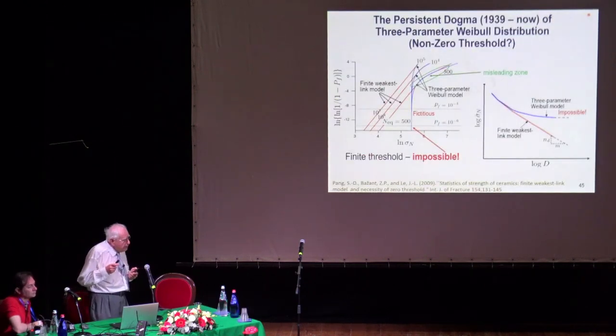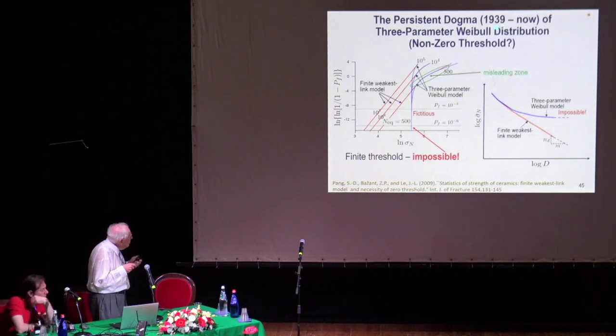Now, in the ceramics literature, and some in mechanics, people use the three-parameter Weibull distribution. That also gives this straight line in a Weibull plot, and curvature. And they are contented with this zone, one zone, where both models coincide. But the three-parameter Weibull distribution has a non-zero threshold; the first one has zero threshold, with only two parameters. Now these are the parameters. If you extend it to the low probability range, 10^-6, there is an enormous difference. If you extend it in size effect, you see the size effect would disappear.